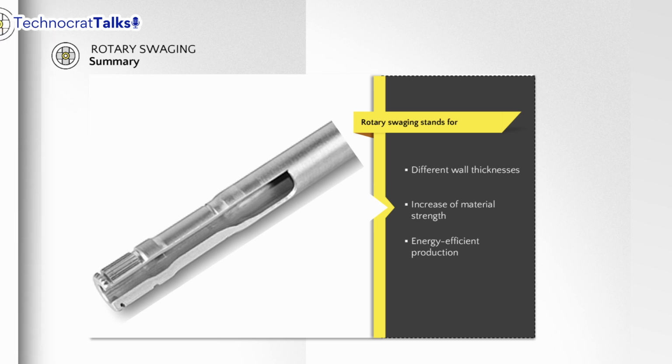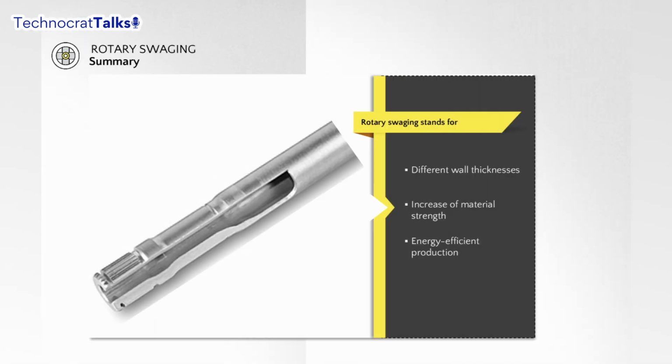The second case is when you have really big wall thicknesses. If we are talking about 10 millimeter wall thickness, for example, then you will see an effect that the material distorts very strongly. So here you have something like 1-2 millimeters of not forming, but real deformation, and we cut this off. But it's absolutely right. If it is small, maybe you can do deburring or polishing, or probably get rid of that.